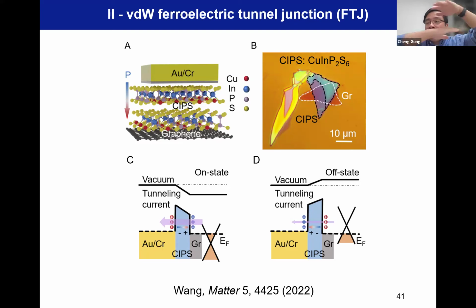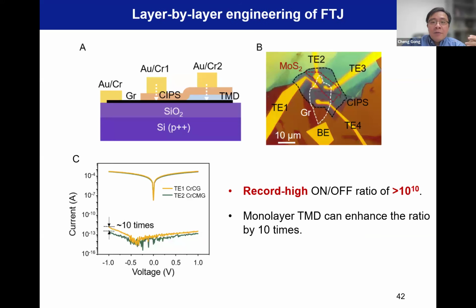TMR, when you change the magnetic layers in a magnetic tunnel junction, you can only change the resistance slightly. So that's why TMR usually is 10% up to 100, 200%. It's just some change of resistance. You can see 200% is just two times. But here you can change the resistance by several orders of magnitude, easily even a billion times. So this is a record high performance FTJ achieved in our lab.